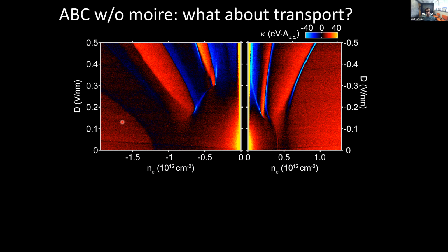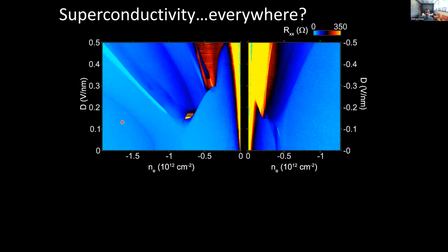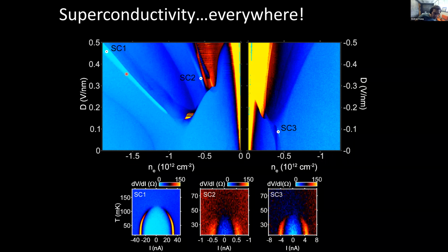It turns out that if you then go back and measure transport, actually this zoology becomes considerably more interesting. In particular, if you now look at transport measurements, you find that the system is actually superconducting in a variety of different densities and dopings that are precisely correlated with some of these transitions in the Fermi surface. So I'll highlight, so this is now resistivity. Sorry, the color scale is missing, but these cyan regions here and there are all superconducting.